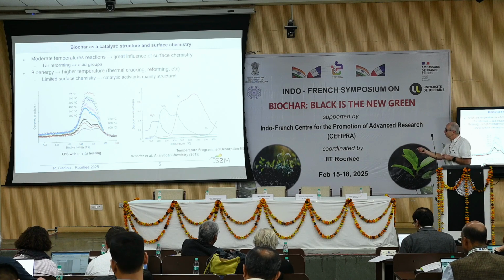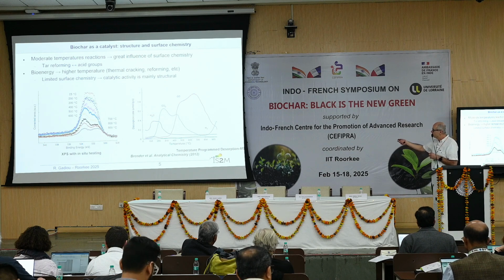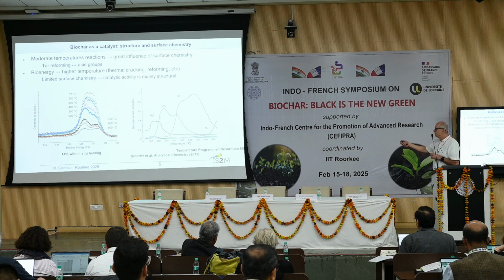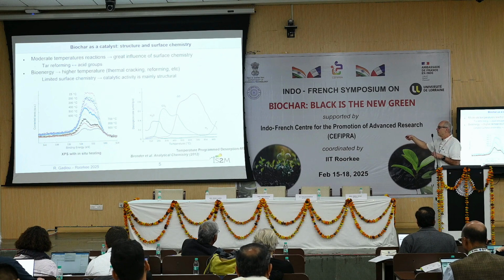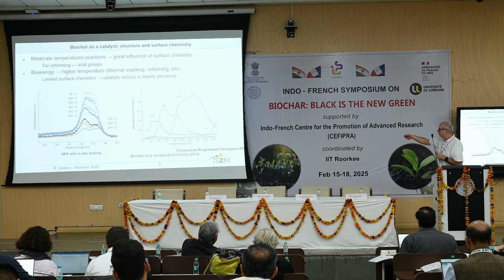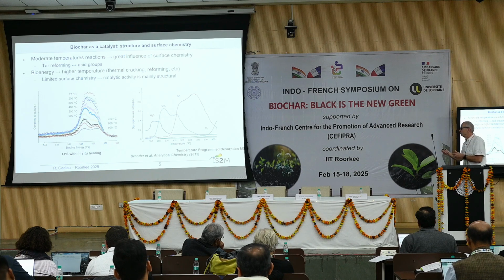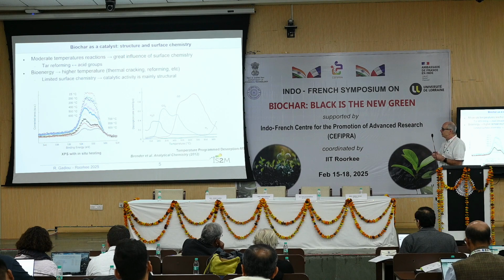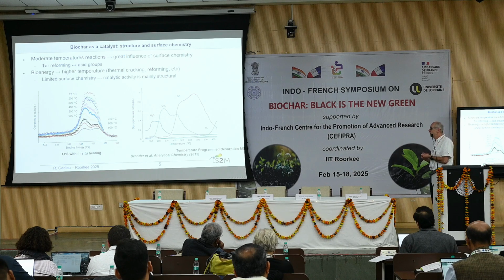hydrogen bond. But also then we have CO2, which is removed, related to carboxyl, and then we have lactone and anhydride and so on, which will be removed, and then we have semiquinones at high temperature, around 700, 800. So that shows that depending on your application, you will not have to deal with the same surface chemistry, whatever you have done with your biochar.